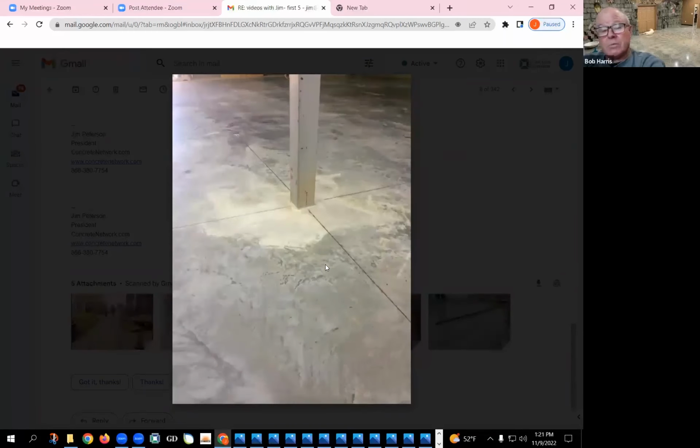Cutting deeper is one solution, but you can't go too deep because you're going to expose too much aggregate. So in this scenario, what we would do is come up with a color match, a dye wash using a gray dye, and somewhere right around 100 grit, you would apply dye prior to the densification process to tone down what I call a hot spot. Painters refer to hot spots as a real bright look, and that's what we have here. So you can tone it down with some color.